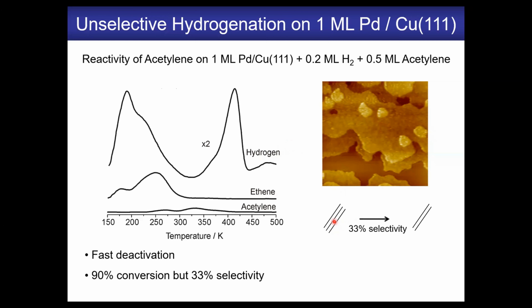And this is really a stark example of an ensemble effect, where in the single atom alloy case, you only have single palladium atoms, which are able to dissociate hydrogen, but they're not able to decompose your reactant because palladium will overbind acetylene and basically break it down to carbon. And that's why you see this hydrogen released here. So in the single atom alloy case, you can break the bond you care about, the H2 molecule bond, but you don't dissociate the molecule itself, which leads to coking and deactivation.